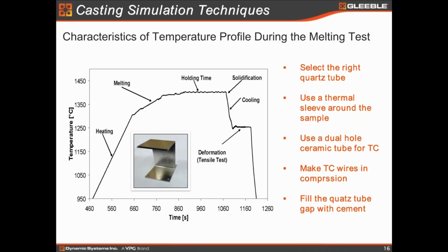But of course, as you can see in the photo here, we needed to insert what we call the magnetic field guide at the back of the pocket jaw to minimize the magnetic stirring, because we know that we are heating the sample by electric current, like AC current. So when you have a current, you have a magnetic field. So we have a guide developed for that to minimize the stirring, so the liquid metal stays quiet. Not like in the molding, where you probably want to stir it to make it uniform. But here, as discussed, the structure you started with is uniform, so you don't really want too much stirring to destroy your sample.